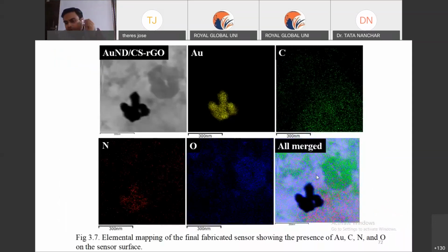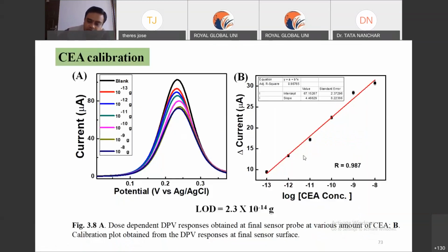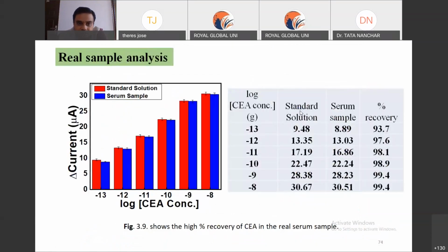Again, we tried this part. This is the normal imaging system, and we did the mapping of the electrode surface. This is the gold, the carbon, nitrogen, and oxygen, and when you merge it all, it is evident that all the materials are present on the surface. This is the final calibration. We increased the concentration from -13 to -8 in order, and you can see the signal keeps increasing. This is the calibration, and this is the real sample analysis.